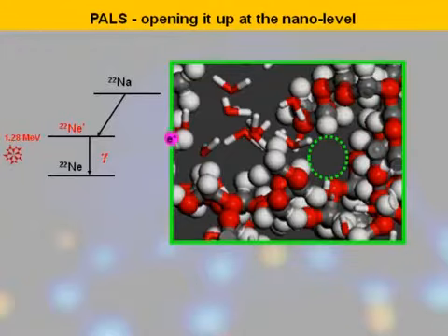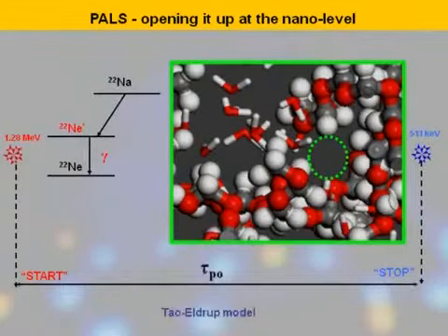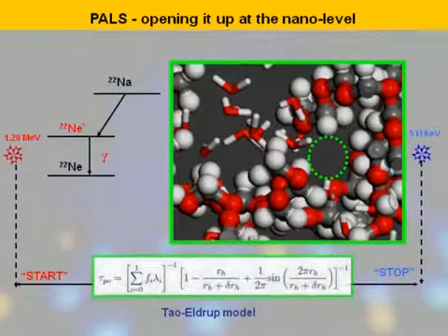This is a metastable positron-electron bound state which can localize in a free volume hole, where it remains throughout its lifetime. The lifetime of the longer-lived orthopositronium is environment dependent, and it delivers information pertaining to the size of the hole in which it resides.